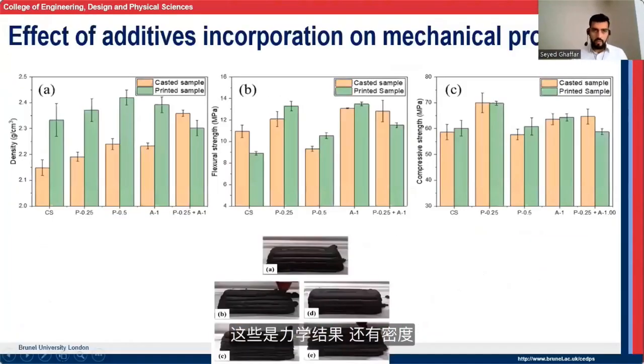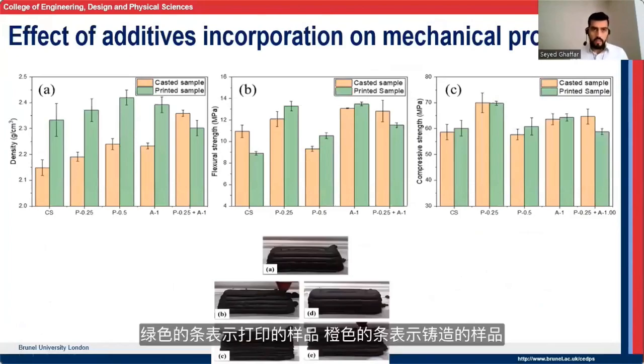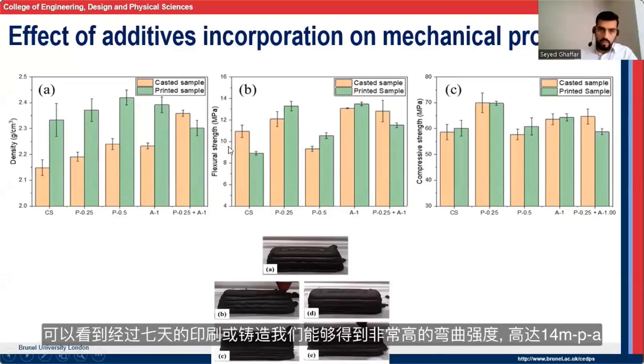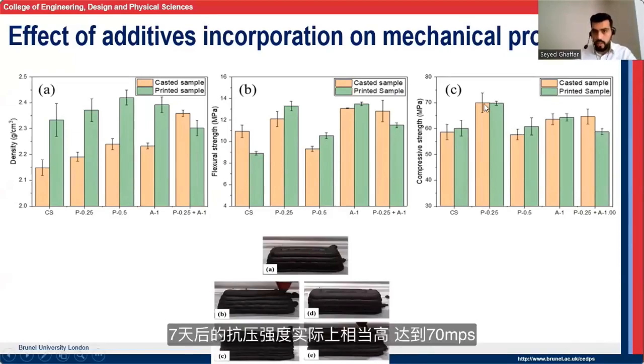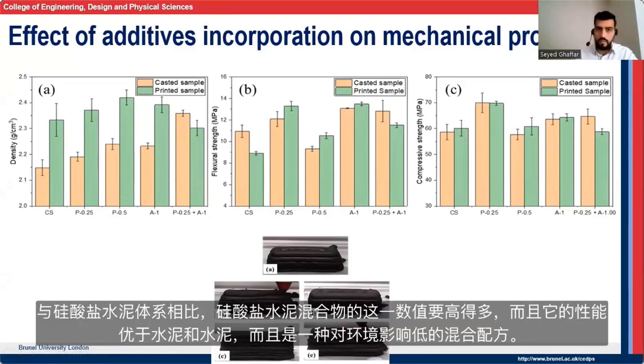So these are the mechanical results along with the density. The green bars represent the printed samples, and the orange ones represent the cast samples. You can see that we were able to get very high flexural strength, as high as 14 MPa after 7 days of printing or casting. And the compressive strength was actually quite high after 7 days, up to 70 MPa. So this value compared to Portland cement mixes is a lot higher, and it outperforms the Portland cement, as well as being a low environmental impact mix formulation.